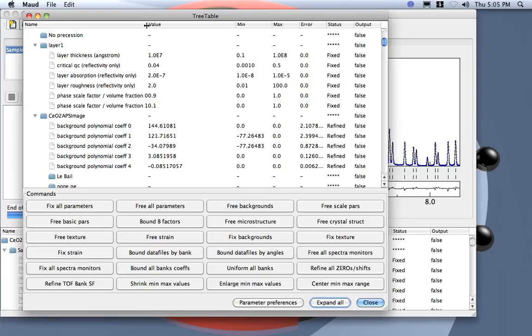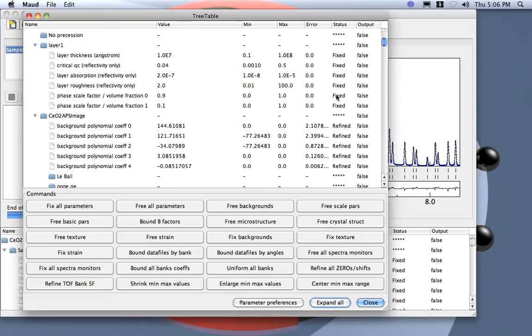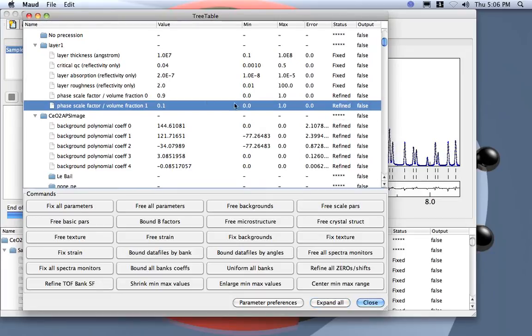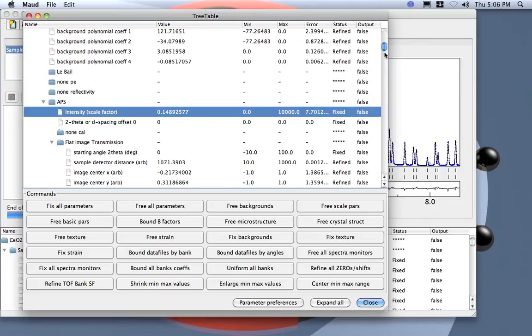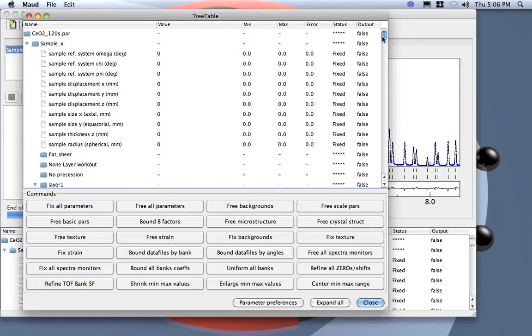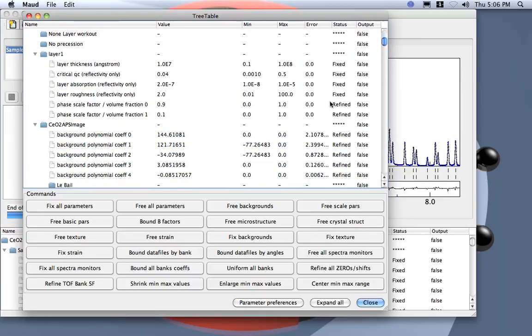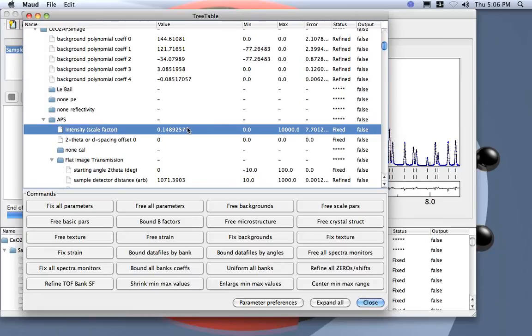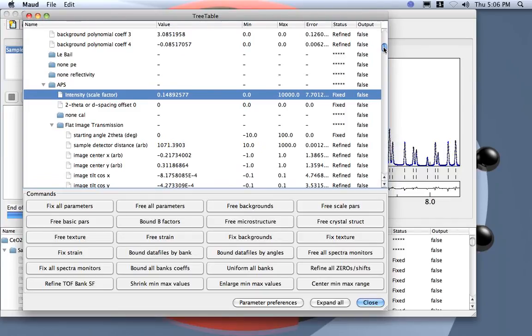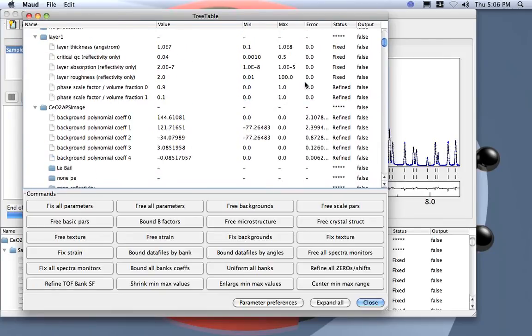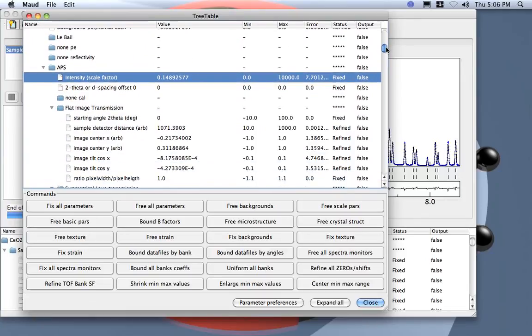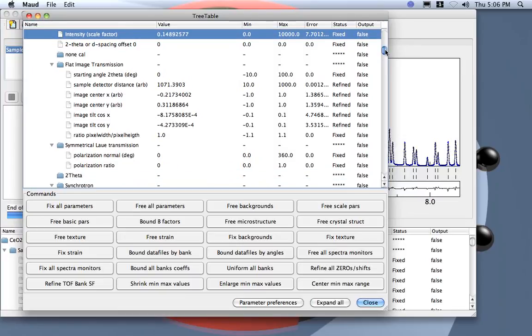In fact I forgot — so now I want to refine the scale factor here, the volume fraction. I don't need to refine the intensity in this case. With the new mode, you can refine both scale factors, and if they both change increasing, the intensity will re-normalize and the difference will be put into the intensity, so I can fix the intensity. This is the new way to work in MAUD, or if you want to work refining only one of the phases and leave the other to balance, then you have to specify in a preference in MAUD how to use the old mode.